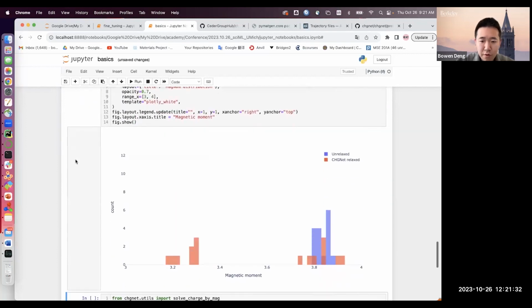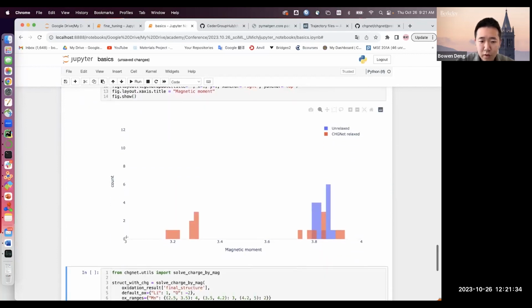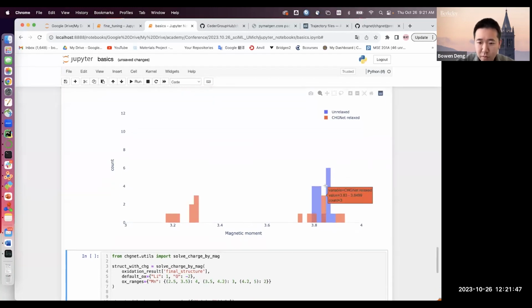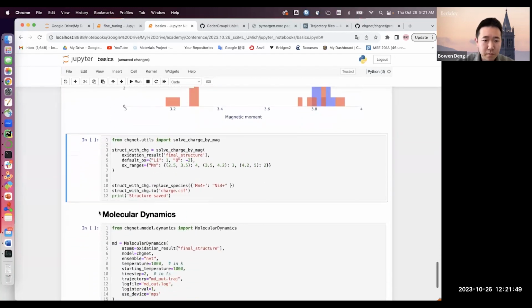And if we try to read what the magmoms are on both the unrelaxed and relaxed structure, here I plot the magmoms between 3 and 4. You can see in the unrelaxed structure, it's only 1 peak. After relaxation, it separates into 2 peaks. This peak corresponds to manganese 4, and this peak corresponds to manganese 3.